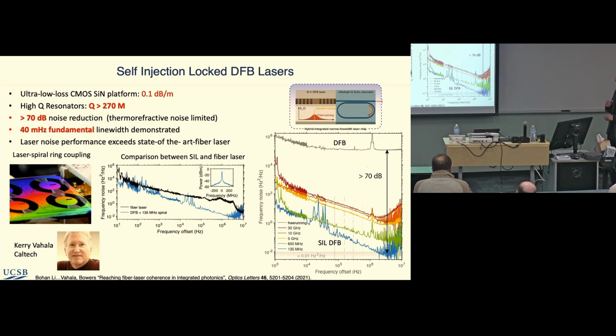The longer you make the cavity, the larger the volume, and the lower the thermal refractive noise. This is a fairly short cavity, I think a 1.4 meter cavity down here. But you get about a 70 dB reduction in the noise, and that makes a big difference.